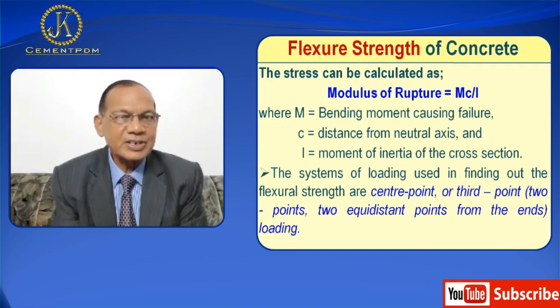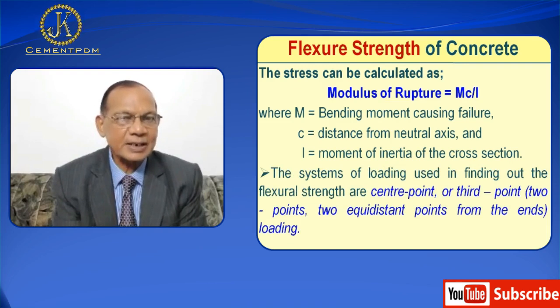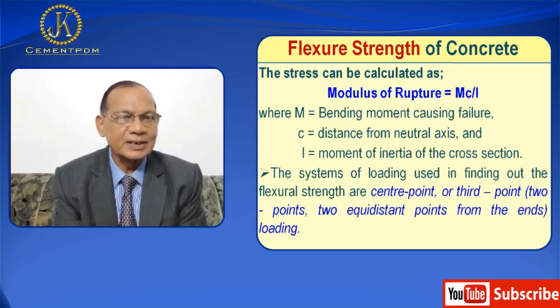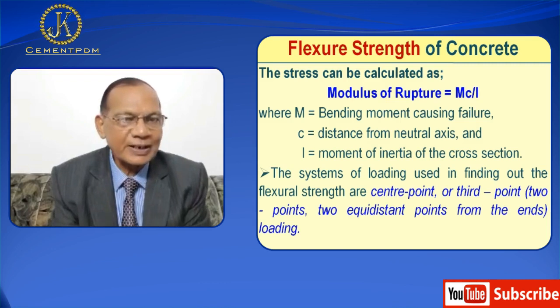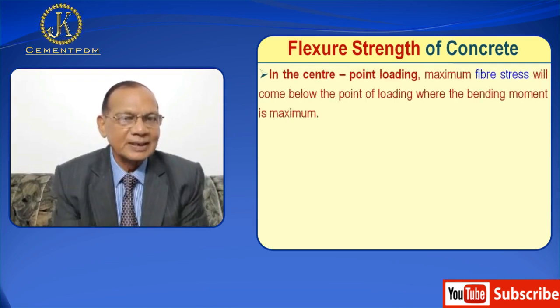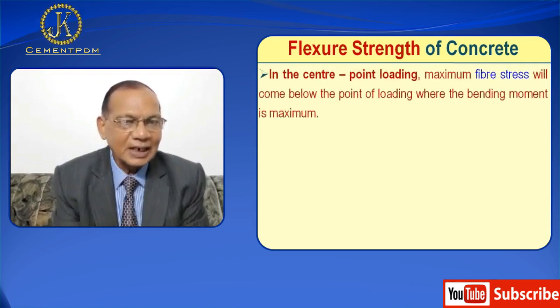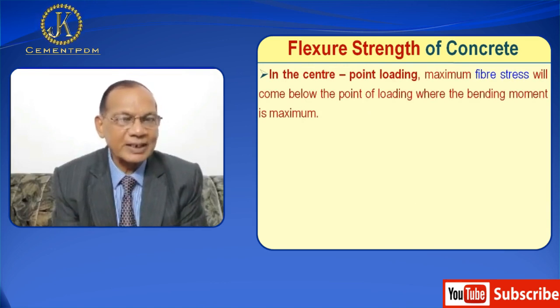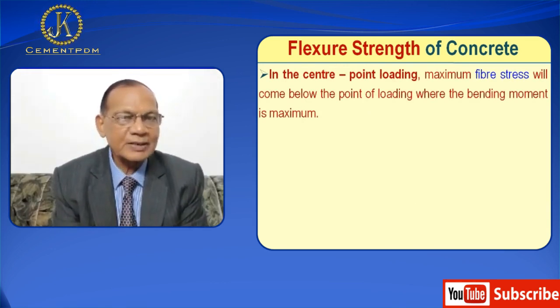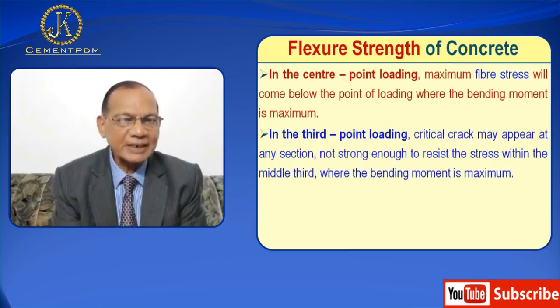The systems of loading used in finding out the flexural strength are center point loading or third point loading — that is, two equidistant points loading. In center point loading, maximum fiber stress will come below the point of loading where the bending moment is maximum.